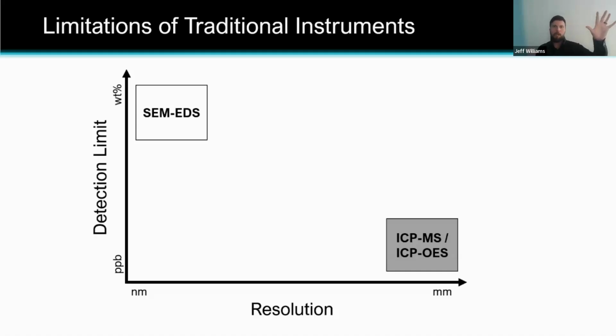And so, kind of in the top left-hand quarter here, a lot of people on this call are probably familiar with SEM-EDS, where you're using an electron beam, and you can see really small features, right, down to nanometer level, and usually under a few tens of microns of area that you're assessing at a time with traditional instruments. And you're only able to really see weight percent level things. So major element chemistries most of the time, and so a large limitation on not just what concentration you could see, but also what elements you can see, right? There's a lot of elements that just are never going to show up with the SEM-EDS system, but still a really incredible tool for imaging, especially on that scale.